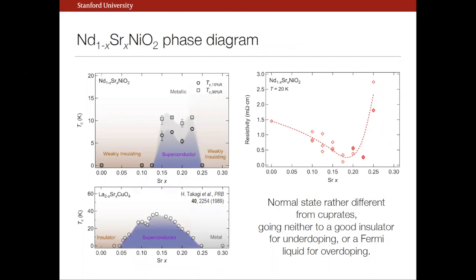So this is the phase diagram. This is down to base temperature of the dilution fridge. So, let's say down to 30 millikelvin conservatively, a superconducting dome that looks like this, and just contrast it with the cuprates. Maybe with the last discussion, I think this is both interesting and shows you the issues that we face. So this is the resistivity at 20 Kelvin right above the superconducting transition.